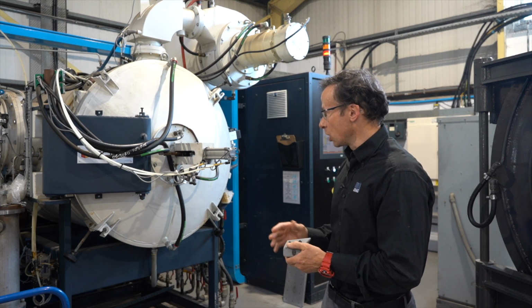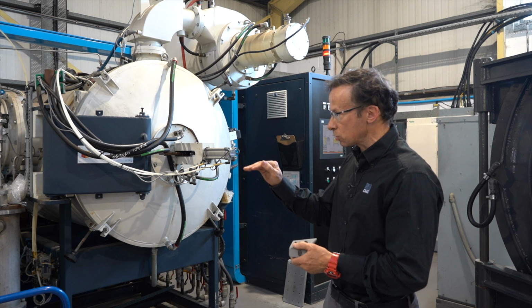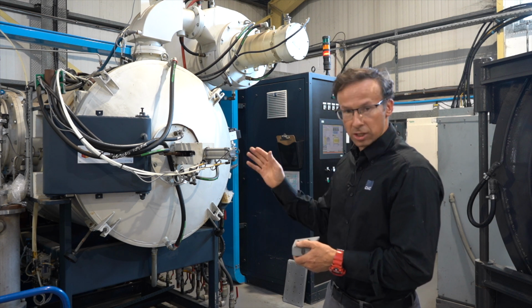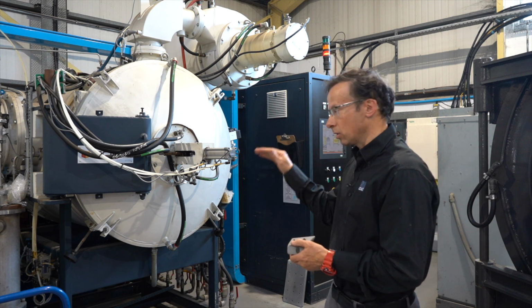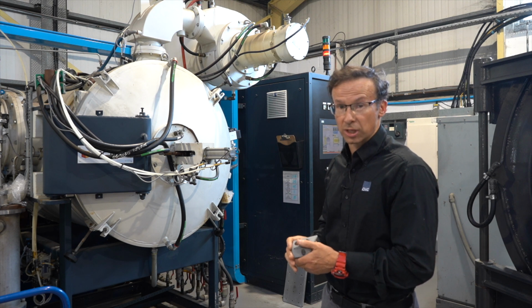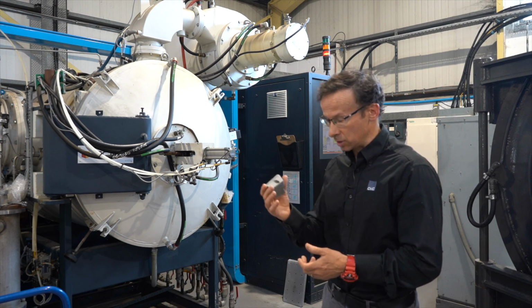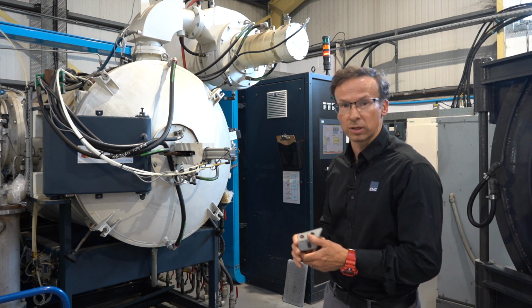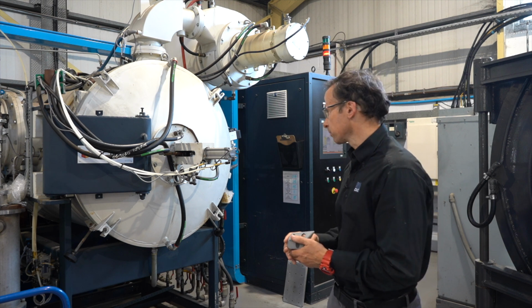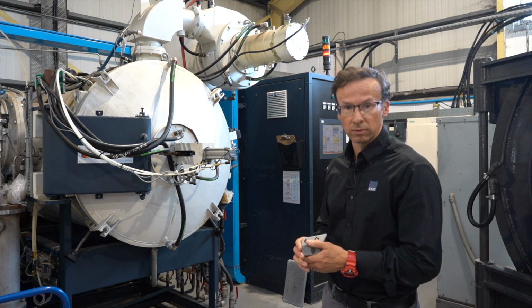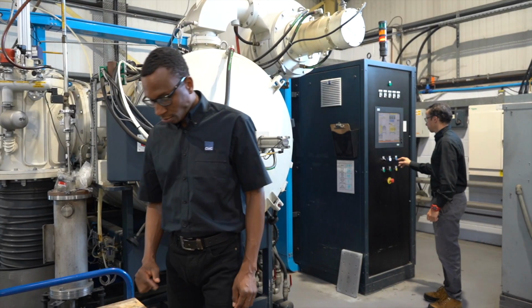So as that carries on, it will take little steps. It will go up to 600 degrees and then we'll carry on going up to about 1360 degrees for this 316L component to be fully densified, and then it will slowly cool down over a few hours.